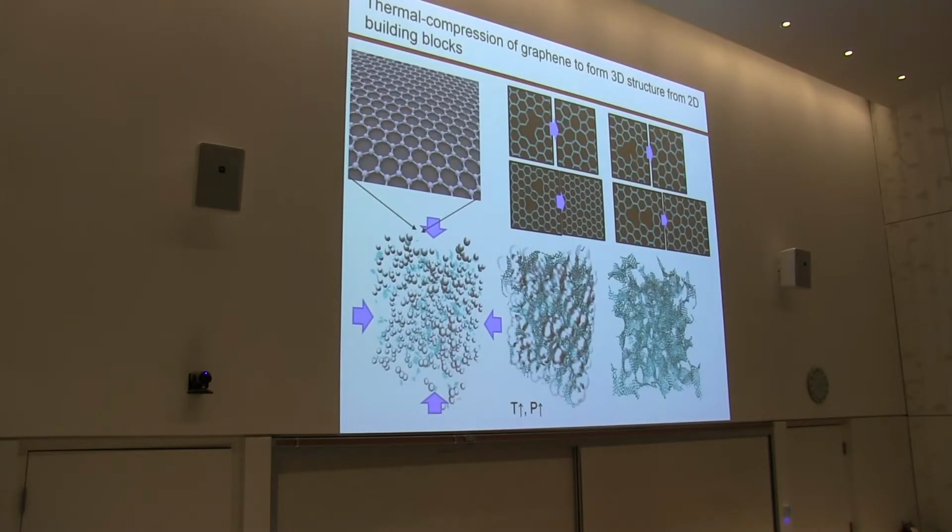That motivated me to look into the strongest material in the world, graphene. Graphene is very light, very thin, and also very strong. But graphene comes in very small pieces, so it's very difficult to apply graphene directly to engineering applications because their size is so small. So I designed a strategy to put a box of graphene flakes together with some nanoparticles. Of course, it's a simulation right now. Then I increase the temperature and the pressure to force those graphenes to fuse together.